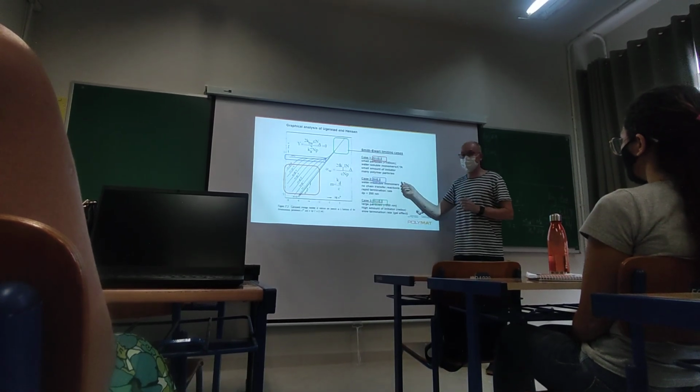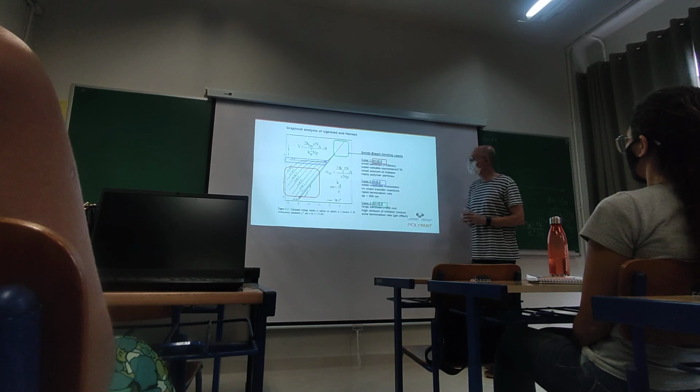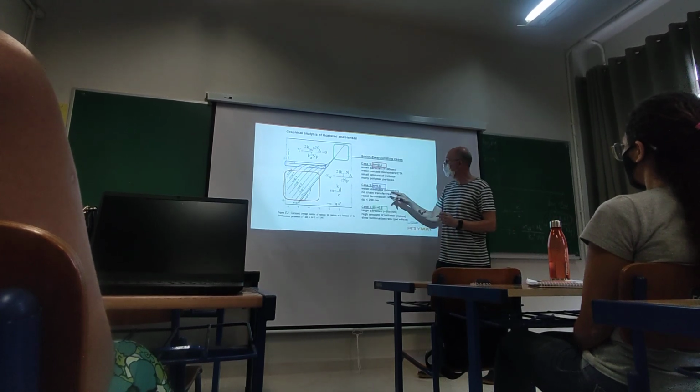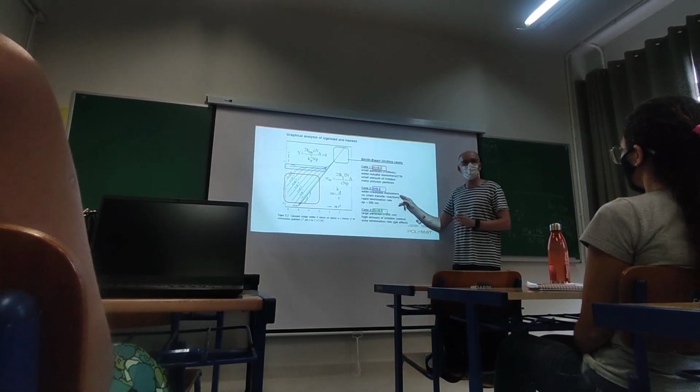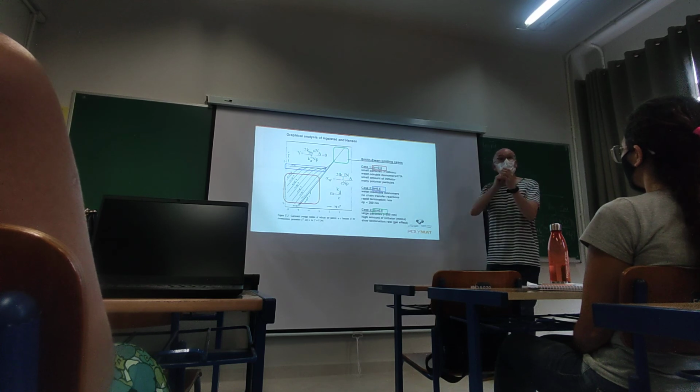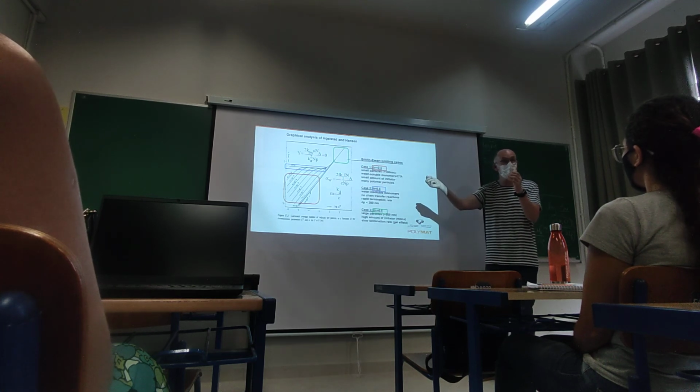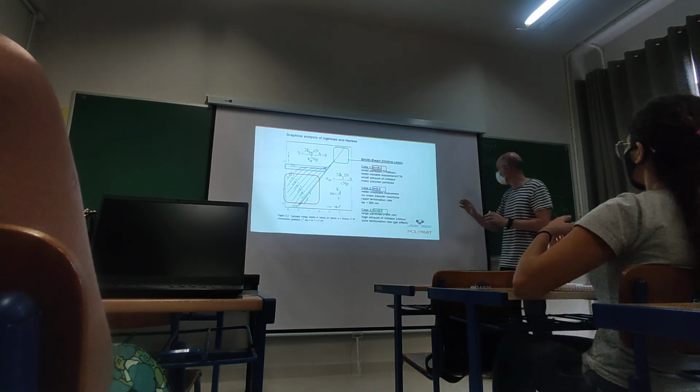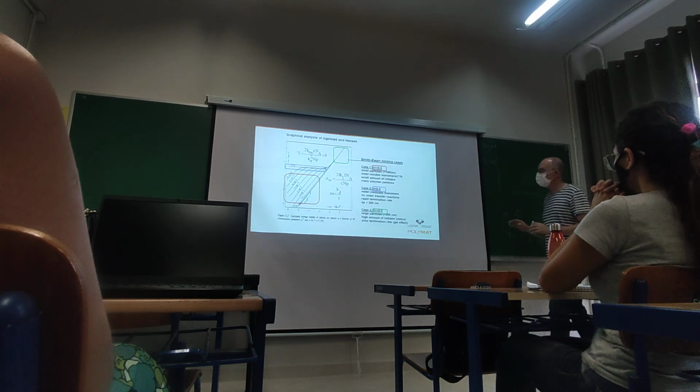Case 2, this is the case that we are interested in, to be in this area, because this is the specific or unique emulsion polymerization. Here we need water-insoluble monomers, like styrene, to have negligible desorption or exit, k_d equals 0. Okay?